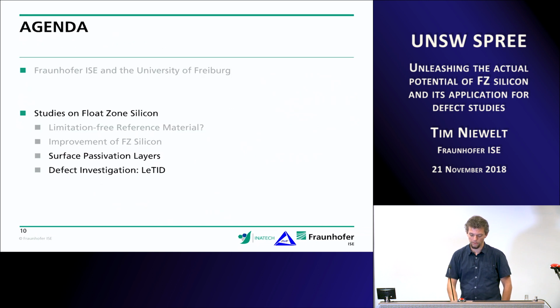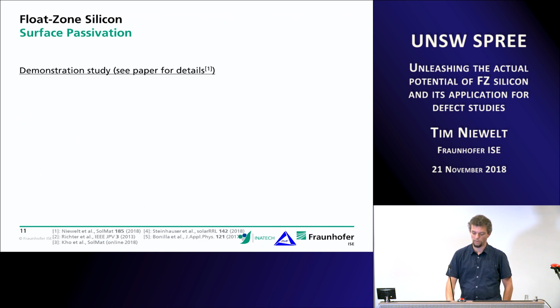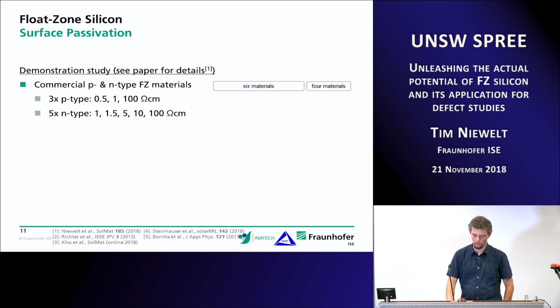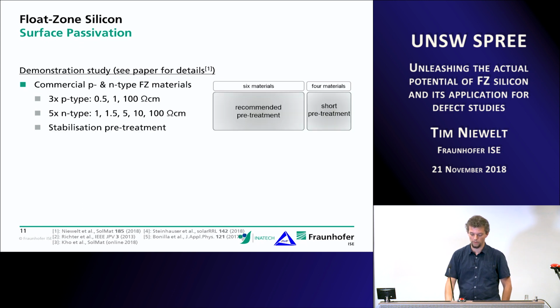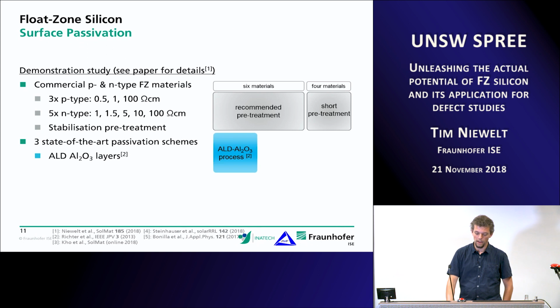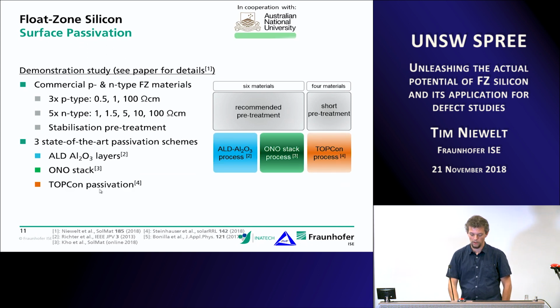Okay, so now we've seen that float zone silicon can be improved, and this material can then be used to do surface passivation studies, which is what a lot of people have done with a material that wasn't as stable as it should have been. So we've performed a demonstration study where we just wanted to compare some state-of-the-art surface passivations. We used 8 different float zone materials, both P and N-type material, with different resistivities. They underwent these pre-treatments to stabilize the bulk lifetime. And then we applied 3 state-of-the-art passivation schemes: an atomic layer deposited aluminum oxide, the ONO stack from ANU, and our TOPCon passivation scheme.